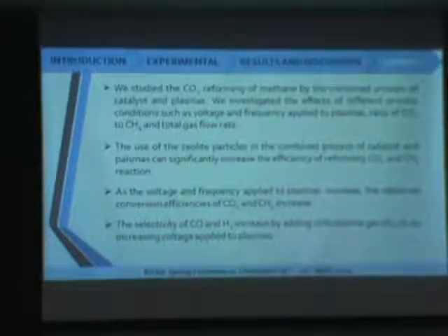We used zeolite particles in the combined process, which increased the effect of the reforming reaction of carbon dioxide and CH4. As the voltage and frequency applied to the plasma increase, the conversion of carbon dioxide and CH4 increases, and the selectivity of carbon monoxide and hydrogen also increases.